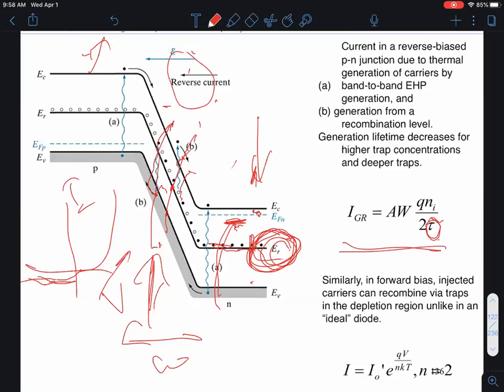And that then adds to this generation recombination leakage current, where it doesn't flatten out as a function of voltage, but increases as reverse bias goes up. And that's what's shown over here. Why does it go up? Well, you get a generation rate of minority carriers, which is given by the intrinsic carrier concentration ni divided by 2 times tau, where tau is this generation recombination lifetime. Okay.